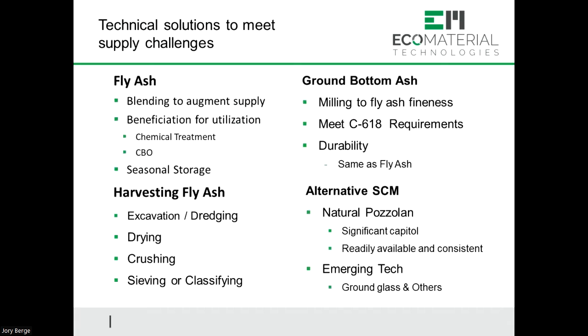So just to kind of summarize ash and ash utilization in your area, for the North Dakota area, you're pretty much looking at Coal Creek, augmenting those supplies, making sure that you have the storage that's required to have that material stored on the off-peak seasons. And you may start to see some harvesting in this area. And that harvested ash will come in the form of an F. It'll probably be just dried, sieved, and put into the marketplace.